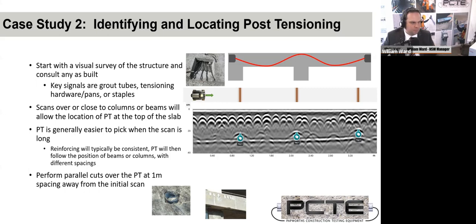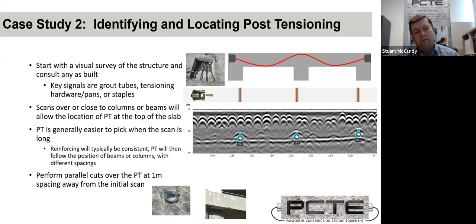And if you don't find them, that's an important time to look elsewhere rather than just take it for granted. It's easier to pick out when the scan's long because the post-tensioning strands could be a meter apart from each other. I would also say just for all GPR scanning, you don't want to do one little scan. Especially when you start a job, you want to do a whole bunch of scanning in the area just to get a feel for what's in the concrete. And for post-tensioning, long scans are better. Reinforcing will be typical 150 mil spacing and the post-tensioning you'll see intermittently.